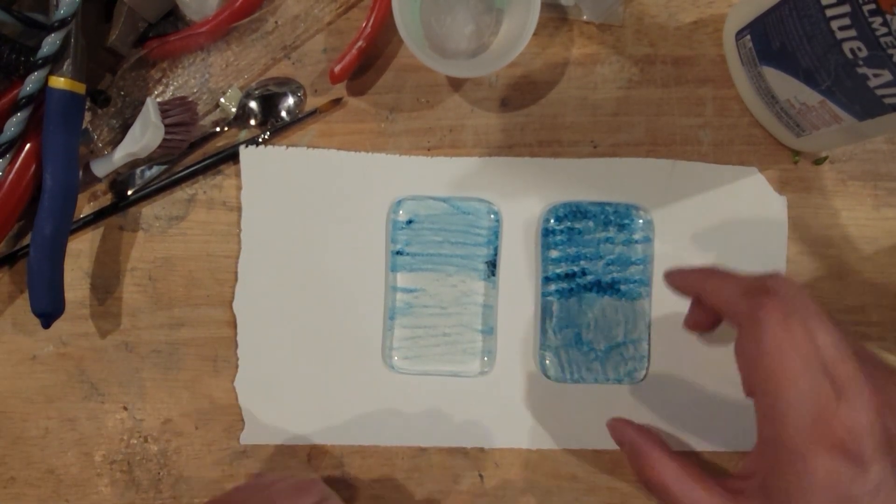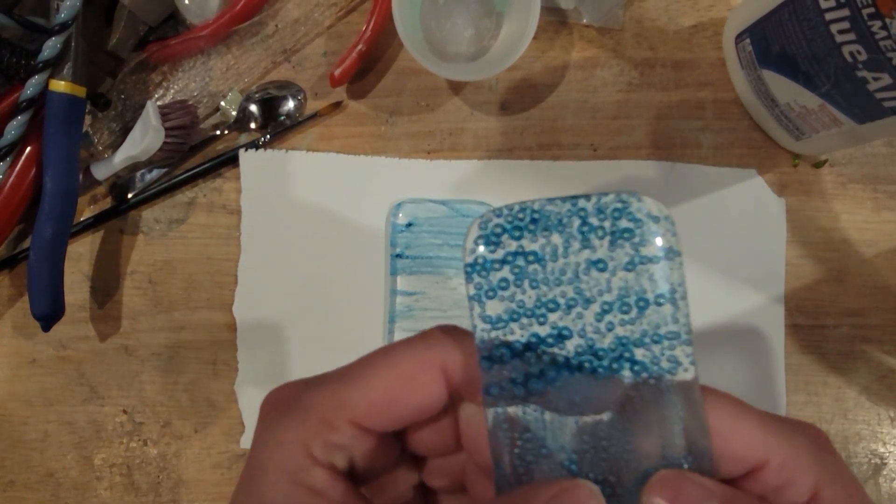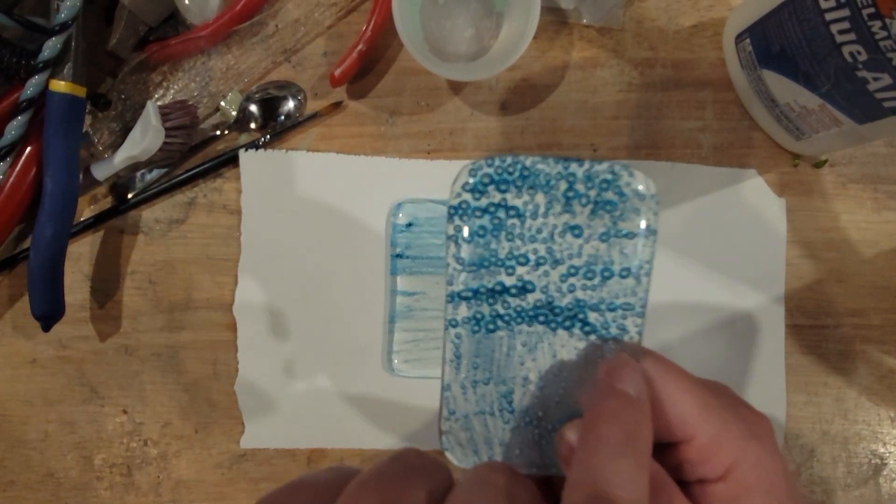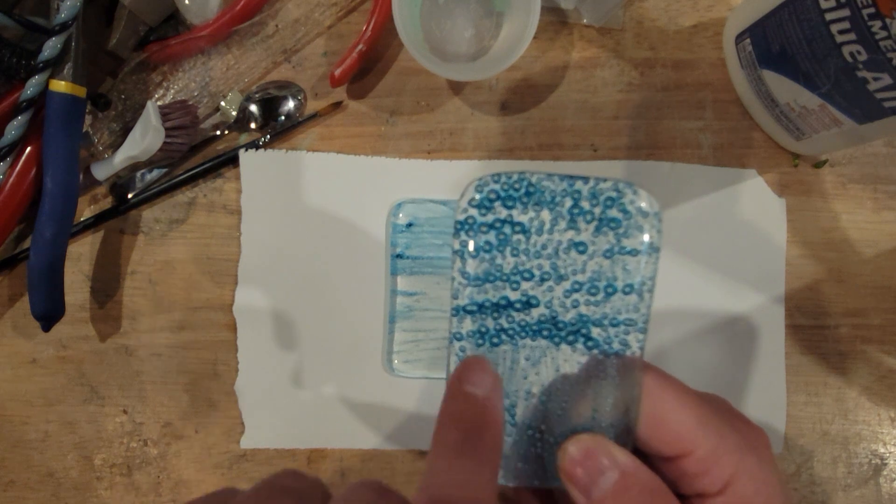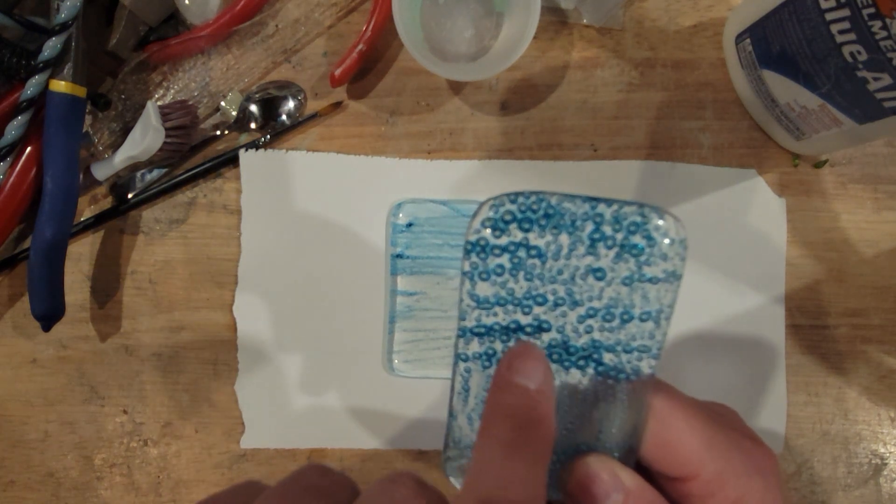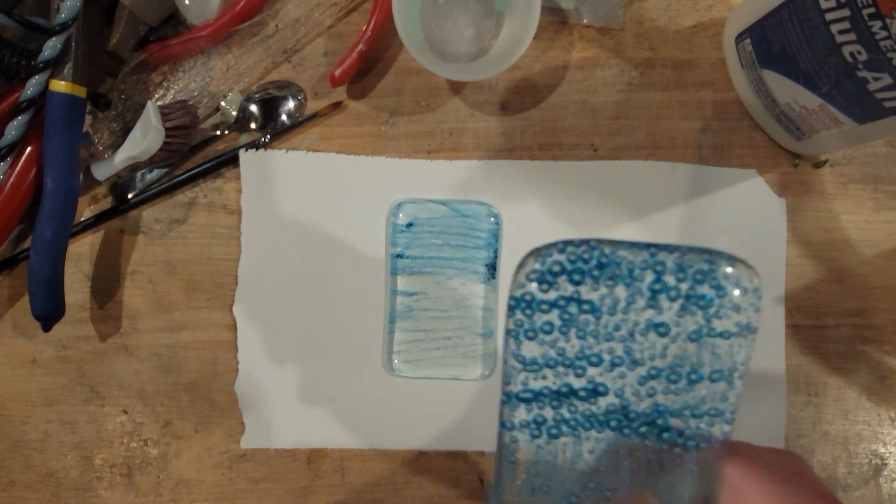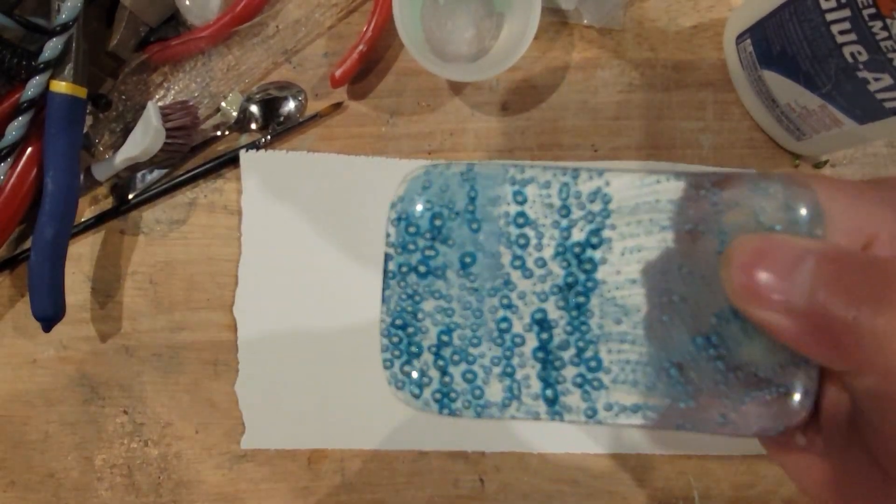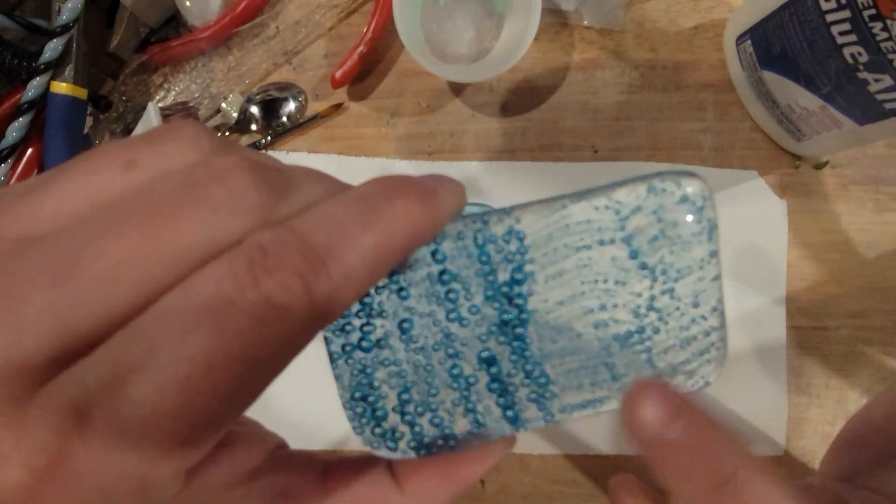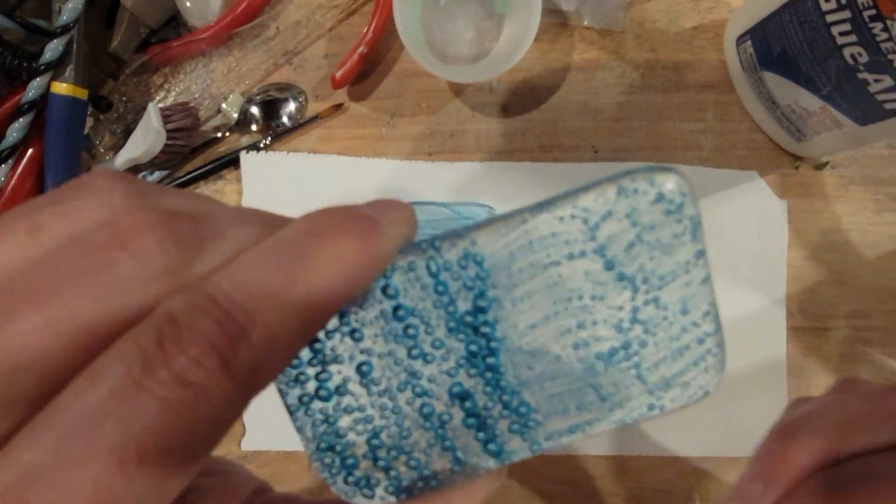This is copper oxide. I'm going to bring it up closer. See bigger bubbles? And this is the line I drew where it was all black and pretty thick. And you can see where they're still dark from where the leftover copper oxide didn't oxidize and make bubbles. So that is where the line is. This is where the thinner brush marks are. You can see them.